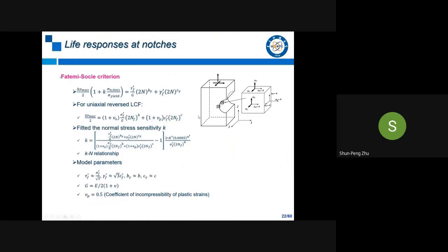And here are just basic ideas of the Fatemi-Socie criterion. This criterion is actually a normal stress correction based on the shear strain amplitude model. The right part of this equation is similar to the Coffin-Manson equation, but this part is under the multi-axial loading condition. So this is a shear stress coefficient and also some other relative parameters. Here we can also simplify it for the uniaxial reversed low cycle fatigue, and this is the simplified equation. Here the normal stress sensitivity parameter K is very important for this model application. I will just ignore the details; more formal information you can find from the work listed at the bottom of the slides.